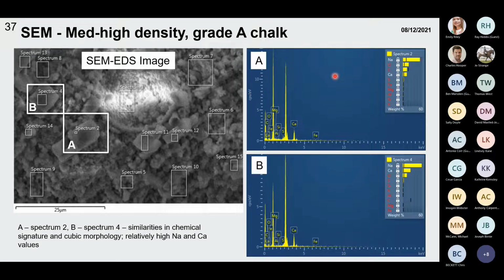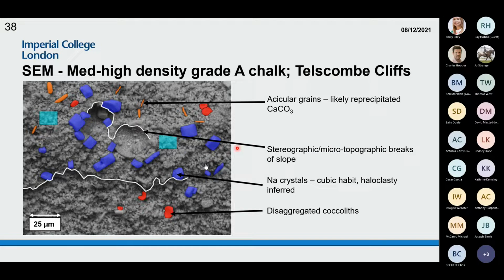So bear with me a moment. This is just where I've undertaken a bit of interpretation. We've got acicular grains here, which are likely to be reprecipitated calcium carbonate. The stereographic surface on these particular samples is not flat. It's quite irregular. You have these breaks of slope, and all these other minerals going on in there: salt crystals, and then disaggregated coccoliths.